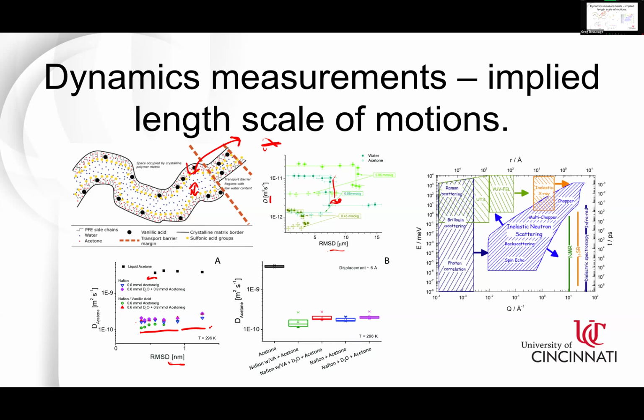But from an inelastic scattering standpoint, the thing that really ruins your experiment is multiple scattering events. Because it's very hard to model something that scatters off of 2 atoms inside the system. So if it has 1 scatter, 2 scatter, how the heck do I put that picture back together in a momentum balance? It's very, very difficult to do. And so you need to keep the samples thin enough that the probability of that event is very low.